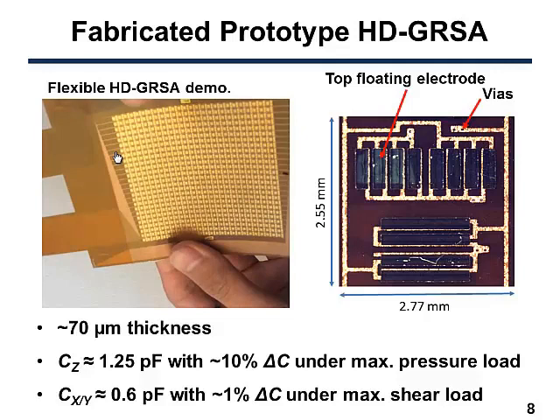The right figure shows the micrograph of one particular sensor node. Each sensor node has a z-axis nominal capacitance of about 1.25 picofarad with about 10% maximum capacitance change at the maximum pressure load. And the XY axis nominal capacitance is about 0.6 picofarad with about 1% capacitance change at the maximum shear load.